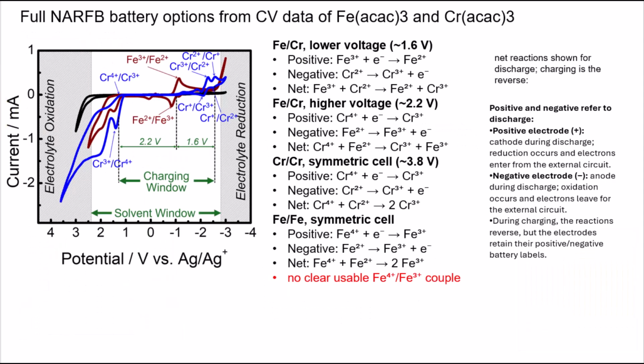Just a little context: the idea is if you wanted to build, say, a non-aqueous redox flow battery, you can look at the individual cyclic voltammetry data for each of the individual redox transitions for the different compounds. What I'm showing you here are data that are overlaid for an iron 3+ acetylacetonate compound in a non-aqueous cell, acetonitrile, with a 0.1 molar TBAPF6 background electrolyte. That's the red line here, and you can see a really pronounced transition from the 3+ to 2+, quite reversible. Then we have a sort of matched compound, the chromium 3+ version, in blue, and you can see more transitions.